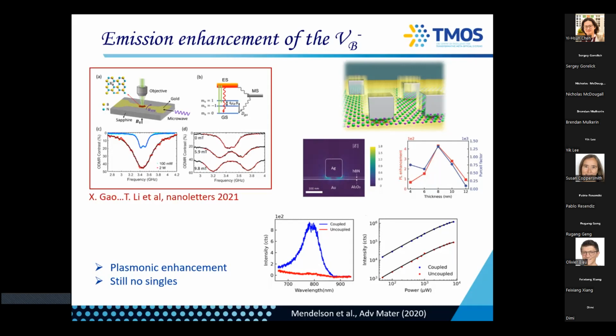In parallel, there was a very nice work from Purdue who, instead of making gap cavities, put the hBN directly on the microwave antenna to generate the microwaves. And they saw another interesting effect, which was an ODMR contrast enhancement. They now see about 50% contrast in the ODMR. Now, the best measurements for NV centers are around 5% or so, 7 maybe. They see 50%. So of course, for sensing, it's great because your measurement time goes to basically a few seconds. You pay the price in terms of your hyperfine. So if you want to do some nuclear spin polarization or some spin manipulation, that's a bit harder because the hyperfine is lost, but the contrast is much higher.